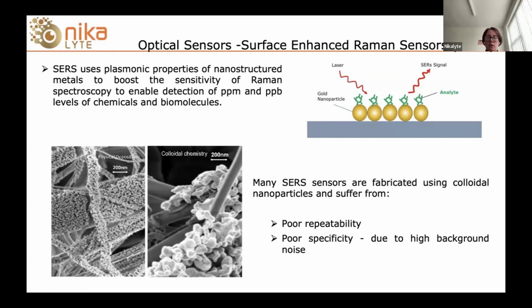The other issue that we've come across with colloidal and chemical substrates is that they can have quite poor specificity. This is due to the fact that there's often quite a high noise background. So although you're seeing those Raman peaks, the weaker peaks are hidden inside the noise. So it's quite difficult to distinguish similar molecules where those weaker peaks are important in identifying what molecule you're looking at.